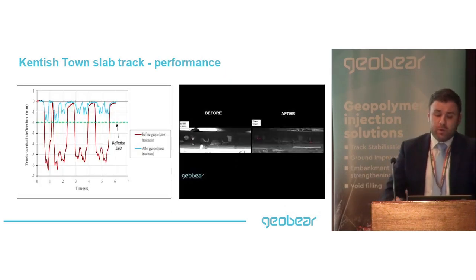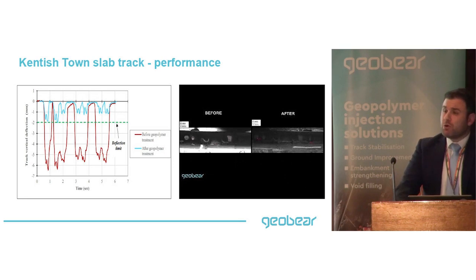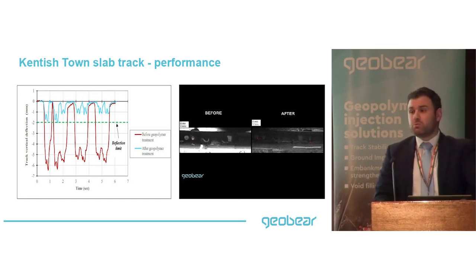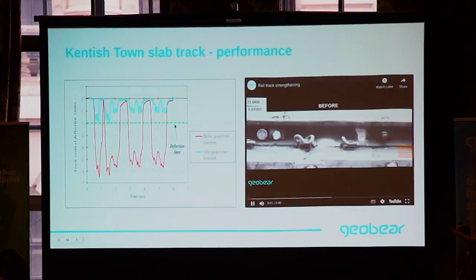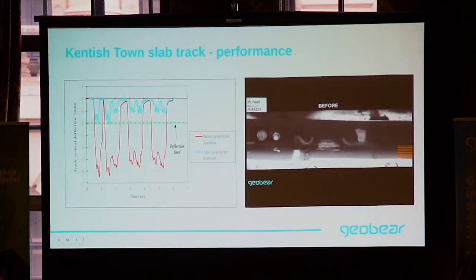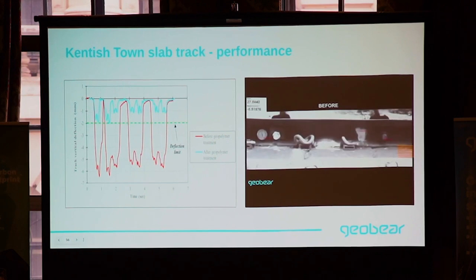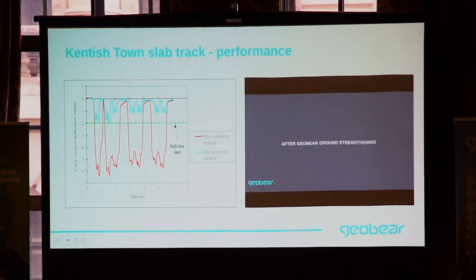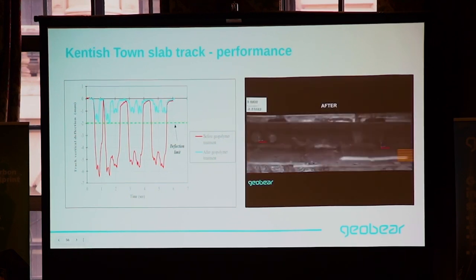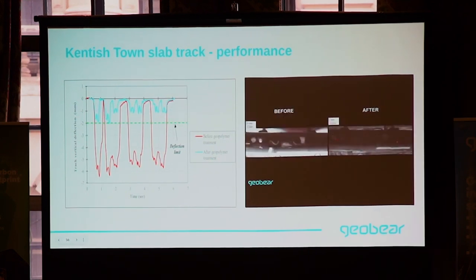The client carried out deflection monitoring, or stiffness monitoring, using high-speed cameras to monitor the track deflection before and after the injection. Before the injections, track deflection was reaching around 6.5 mil. Following the injections, that was reduced to just shy of 2 mil, which puts it in the ideal range for what the track deflection should be on a normal, operational slab track.